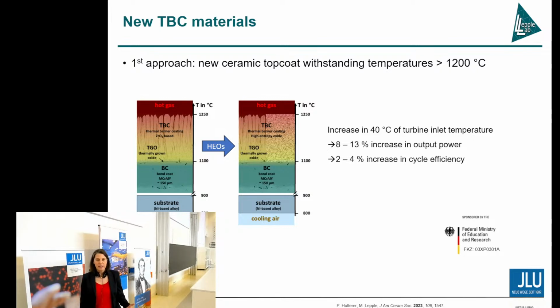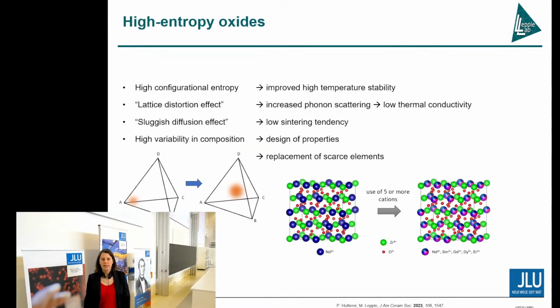And by increasing the combustion temperature or the surface temperature by 40 degrees centigrade, we actually can increase the output power by 8 to 13%, and also can increase the cycle efficiency up to 4%. What we are doing, we are investigating a new materials class, the so-called high entropy materials or high entropy oxides.